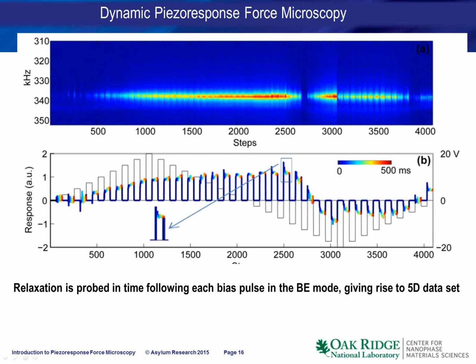An example of more complex piezoresponse spectroscopy is what we call dynamic PFM. So in this case, we perform the ferroelectric switching, but we do not simply average the signal after each pulse. We actually follow the evolution of the signal as a function of time. So this rainbow color scheme after each bias pulse corresponds to the time evolution of the signal. And you see that in some regions, there is virtually no evolution, so the signal is set. In some other regions, you can see a very visible relaxation of the PFM signal after the bias pulse, for example, in the region which is delineated by the square. So in this case, we probe the relaxation in time after each bias pulse in the BE mode.